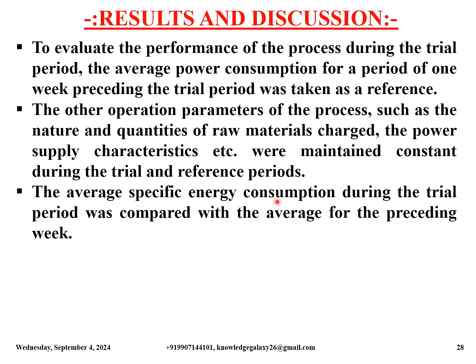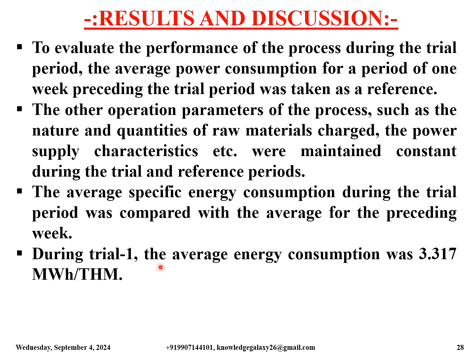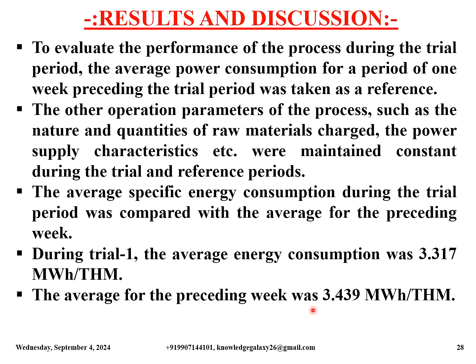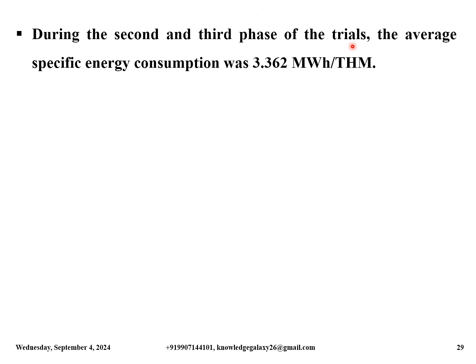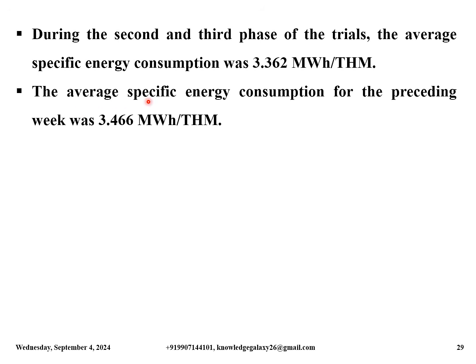The average specific energy consumption during the trial period was compared with the average for the preceding week. During trial 1, the average energy consumption was 3.317 megawatt hour per ton hot metal. The average for the preceding week was 3.439 megawatt hour per ton hot metal. During the second and third phase of the trials, the average specific energy consumption was 3.362 megawatt hour per ton hot metal. The average specific energy consumption for the preceding week was 3.466 megawatt hour per ton hot metal.